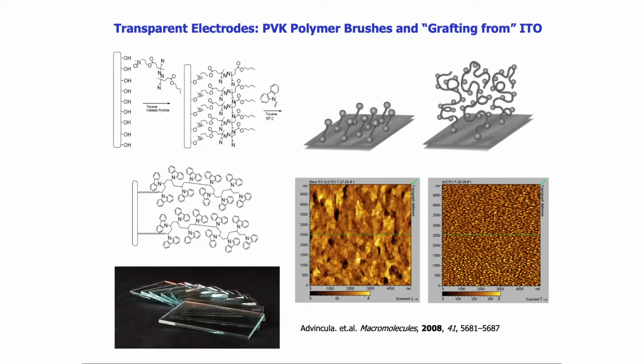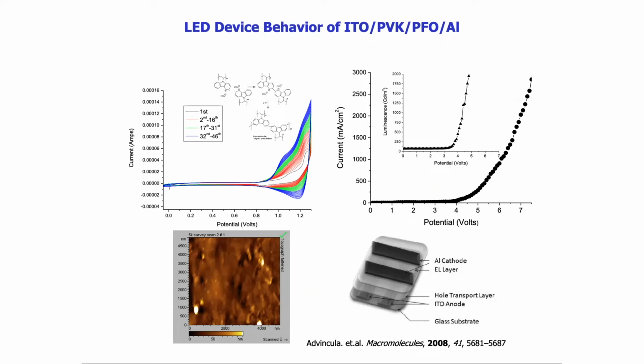You can see that this is a very rough layer by AFM. But by grafting the initiators, AIBN and so on, and grafting polyvinyl carbazole as a polymer brush, you can see a smoothening of the surface, again by AFM, as shown here. Now, not only do we smooth the morphology, we can actually use this to improve the performance of devices, as in this case with an LED device using, again, polyfluorene and cross-linked PVK. The resultant polymer grafting gave us lower turn-on voltages.